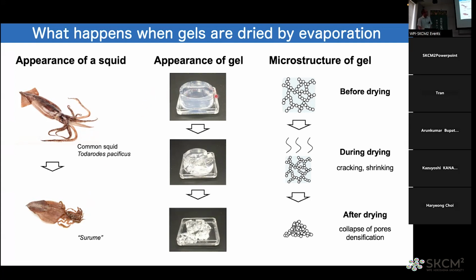And this is the silica gel. Silica gel also causes shrinkage, but in this case, the gel is friable. So not only shrinkage, but also breaking and cracking of the gel occurs. This is the schematic of the microstructure of the gel before drying. During drying, there is shrinkage. And after drying, the whole thing is collapsed. So you can't normally obtain aerogel in this process.